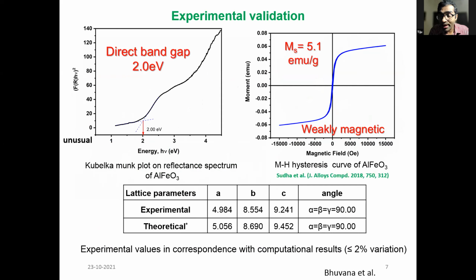And it has a direct band gap. Aluminum ferrite standalone has a band gap, in terms of predictions, of 2.6 eV. In practice, it is 2 electron volts. Please note that this is somewhat anomalous. It is unusual because typically it's the other way around. The approximations that go into simulations, such as the one that I showed you earlier, are such that very often it results in underestimation of band gap. But here we are actually overestimating the band gap when compared to the experimental value. And it is a puzzle why it is so, and we are exploring that currently.